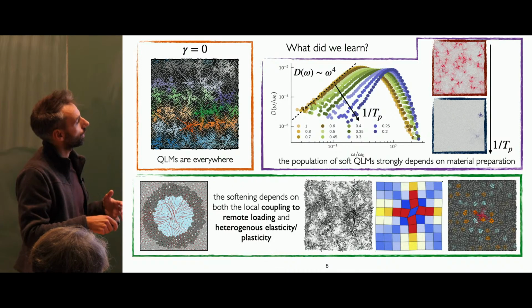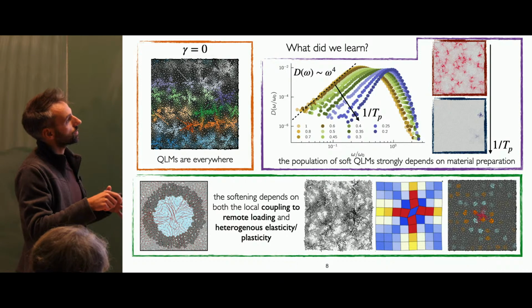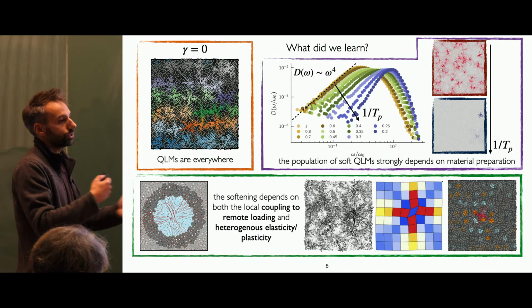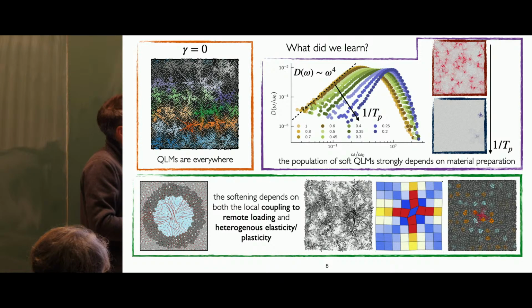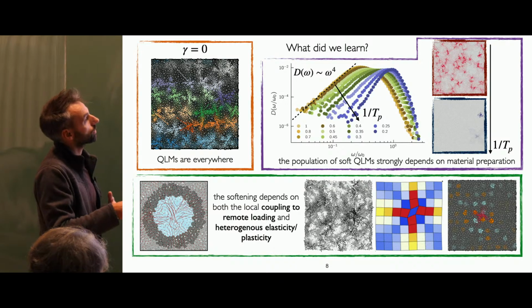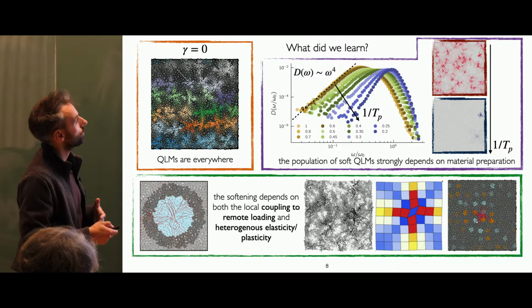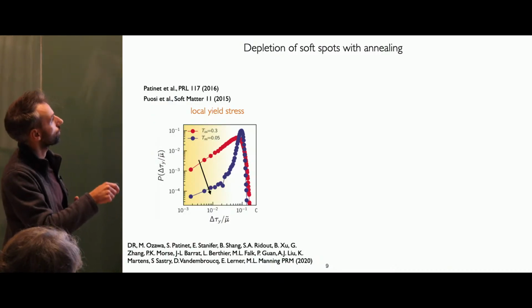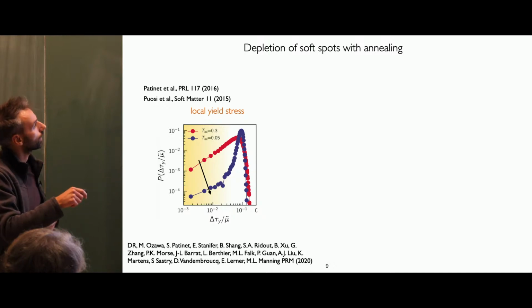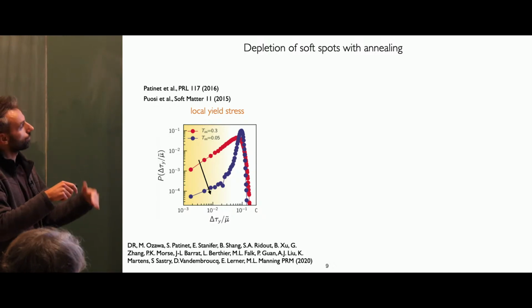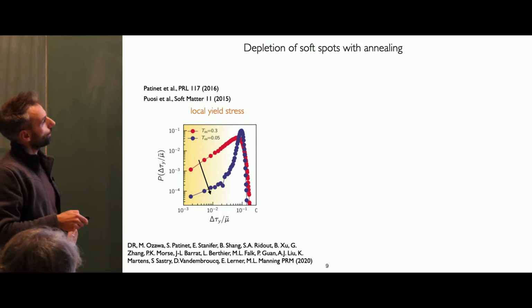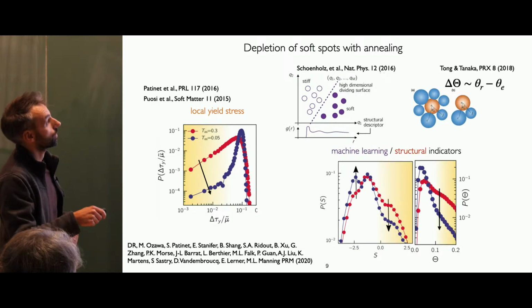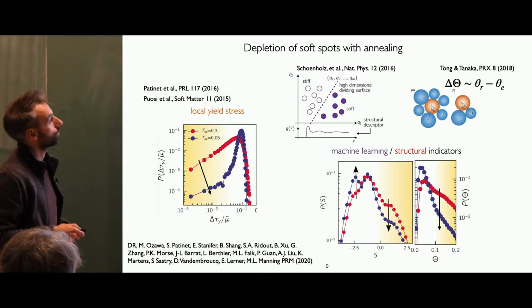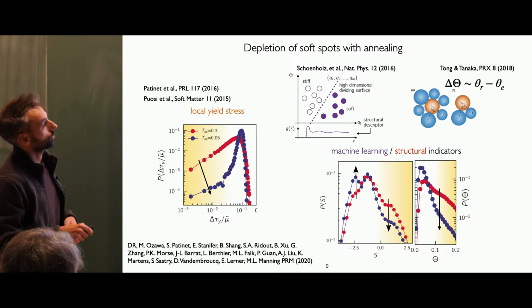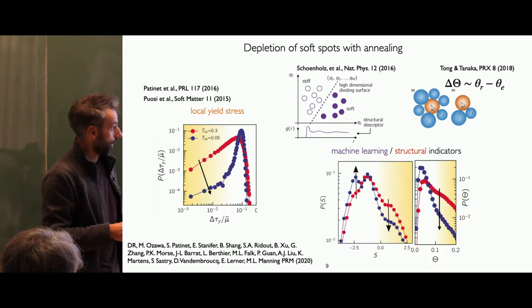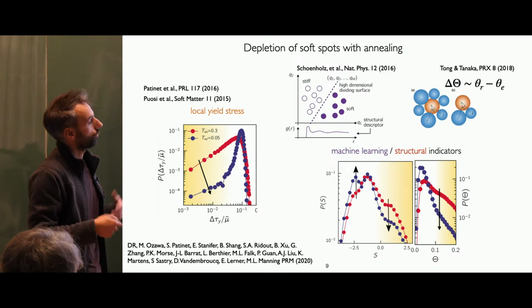And the combination between elasticity, plasticity, and the quenched disorder that you have in a glass will lead to different responses. And this type of depletion was not only seen, of course, in methods which are based on the energy landscape, but also in the local yield stress. So if you take a high temperature glass or a glass which is annealed very slowly, you have a depletion of defects. And you also see this in machine learning based methods like the softness that Andrea will talk about, and also in some purely structural metrics, where you see a depletion of unfavored structure.